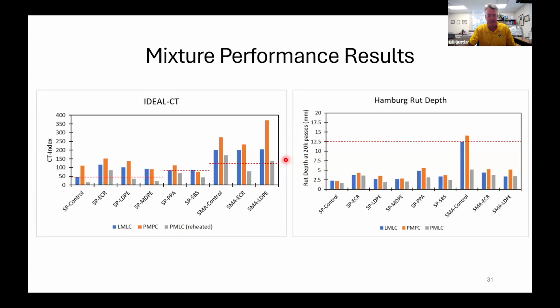The red lines indicate the thresholds. You can see the elevated CT index for the dense gradeds that we selected, and then the SMA being higher. And you can see the designs were either like the control, toeing the line, but a lot of the plastics and rubbers and SMAs were exceeding the crack requirements even during production, even some of the reheats. We have different criteria for the reheat, so you'd have a second bar or second line that would be lower. I didn't show that. On the Hamburgs, as we heard before from fans, stiffness is not your problem with plastic mixes. The SMA control is the one that was giving us a little bit of trouble with the low dust, and you could see it in the performance test results on the Hamburg.